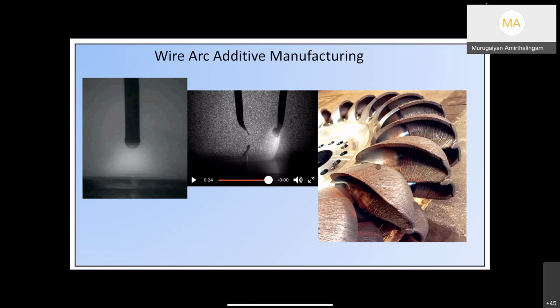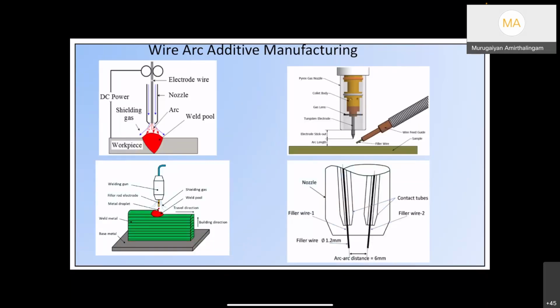Okay, good. So as I said, in wire arc additive manufacturing, we use a welding torch, a conventional welding torch, to produce components. It can be a gas metal arc based process, or even a gas tungsten arc weld process with external filler additions. So we can add external wire, and then arc heat melts the wire, and then that can be deposited. We deposit layer by layer, and multiple weld beads are deposited to fabricate the net shaped component.